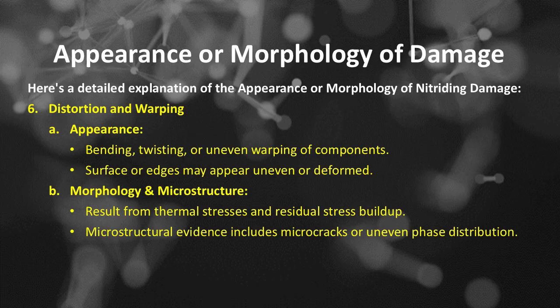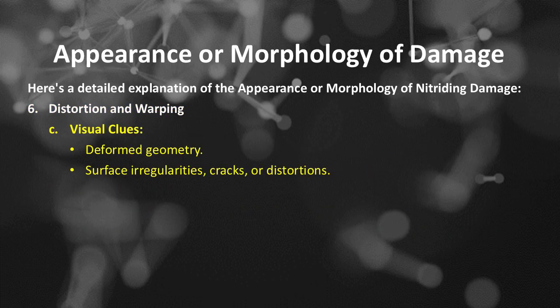Morphology and microstructure result from thermal stresses and residual stress buildup. Microstructural evidence includes microcracks or uneven phase distribution. Distortion and warping visual clues: deformed geometry, surface irregularities, cracks, or distortions.